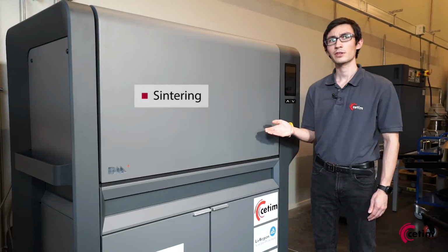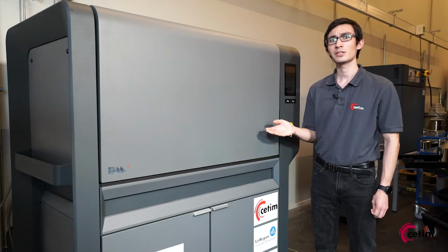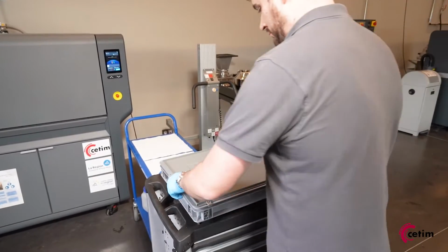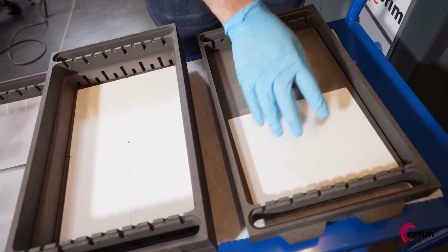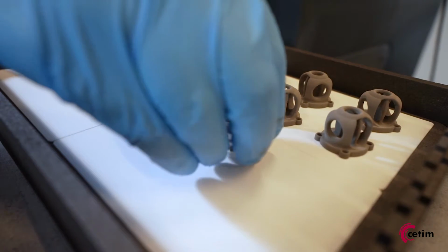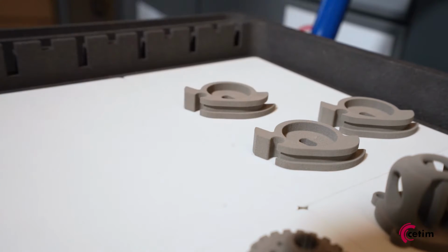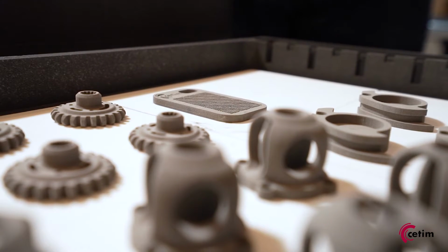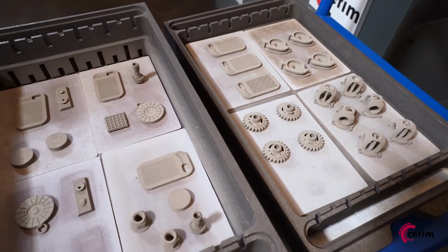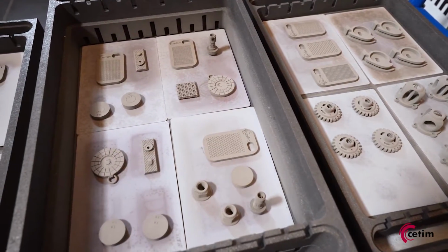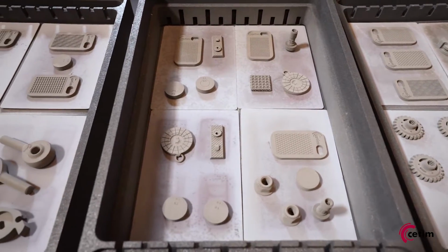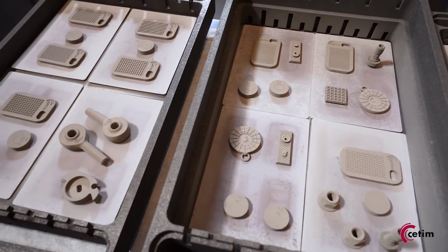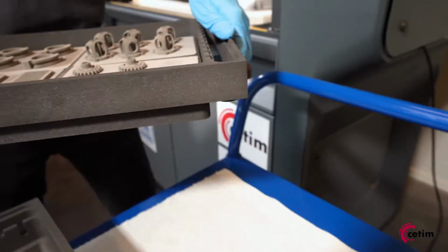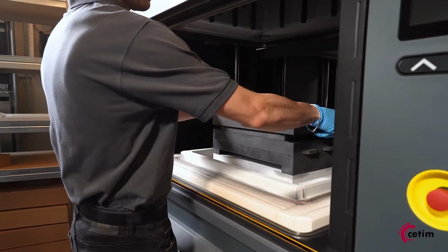Sintering is a thermal treatment for bonding particles by heating the green part just before its melting point. During the sintering, the parts sometimes need a little help, and they are usually placed on top of a setter to prevent the distortion during the densification of the part. The debinding step is included in the profile just before the sintering, and this is a necessary step to obtain a 100% metallic part. Parts are placed on multi-level graphite trays surrounded by the heaters.